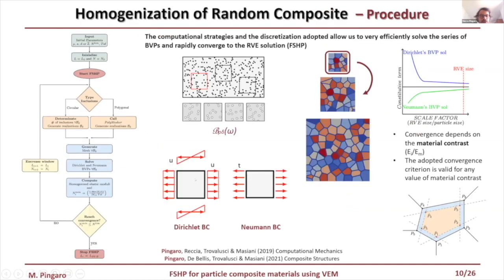The procedure illustrated has a high computational cost. The main problem is that it does not permit performing a series of parametric analyses. For this reason, the procedure has been automated in a code totally implemented in-house, the so-called fast statistical homogenization procedure, FSHP. By using FSHP, it's possible to obtain convergence of the procedure quickly, in more or less a couple of hours.